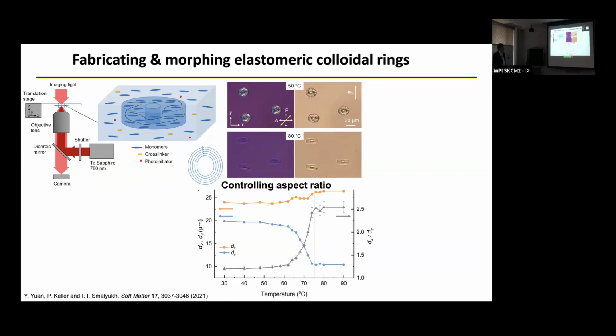And then these donut-shaped particles can respond to external stimuli in a highly interesting way. So you can see these particles would shrink or expand in different directions as you heat them and cool them. So for example, this donut is becoming elongated in one direction, which is perpendicular to the far-field director, the average orientation of liquid crystalline molecular ordering, and shrinks in the other direction. And with that, we can choose conditions to open and close the hole inside. So with that, we can change the topology of these colloidal particles, going from a genus 1 torus to an object without a hole that is homeomorphic to a sphere, because this process allows us to anisotropically shrink and expand such objects.